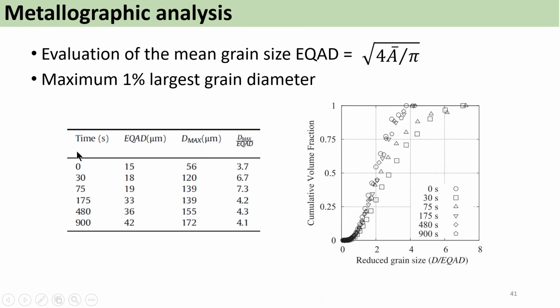So before, of course, we've done some validation with microstructure. We looked at the grain size, equivalent area diameter. We looked at the maximal grain size in the microstructure using metallography. We looked at the distribution of grain size. And as I said before, in these two curves, which correspond to the squares and triangles, early on in the treatment you can see a much wider distribution. Here it's Dmax over EQAD, a much wider distribution early on in the holding than afterwards.